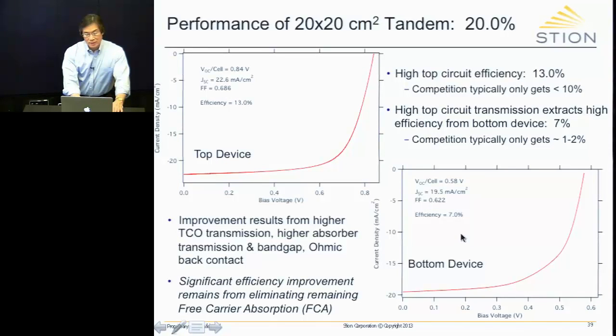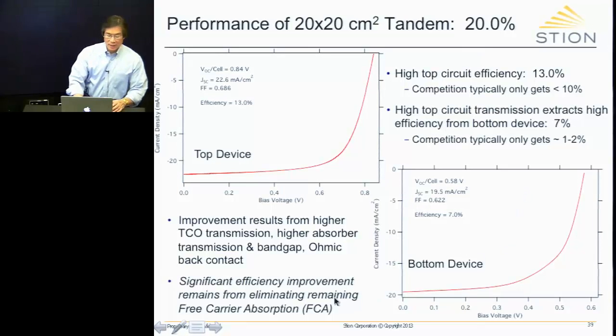The bottom device, we've been able to extract 7% from the bottom. And in actuality, we're prouder of this result than the top device, because extracting that much efficiency from the bottom device was key to getting to high efficiency. Most people get about 1 to 2% at most from the bottom device. I made a comment here, and that is that, as you saw from the previous slide, we can still improve the amount of efficiency we extract from the bottom device by eliminating even further the free carrier absorption.